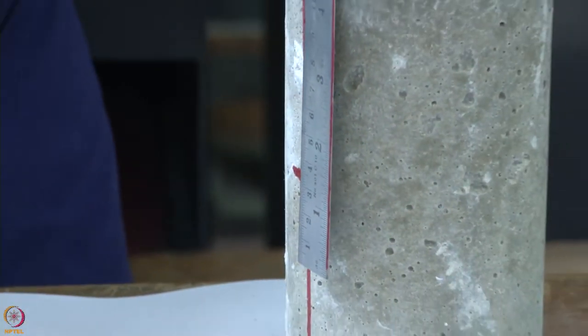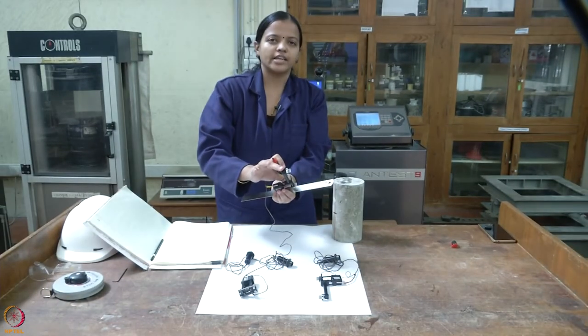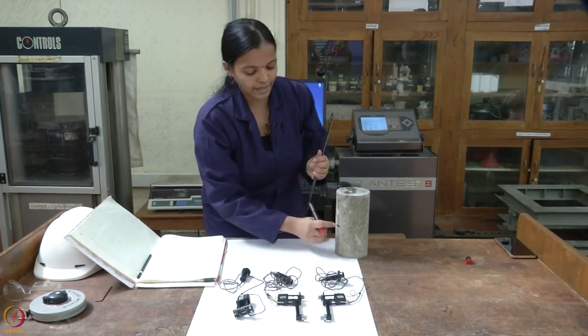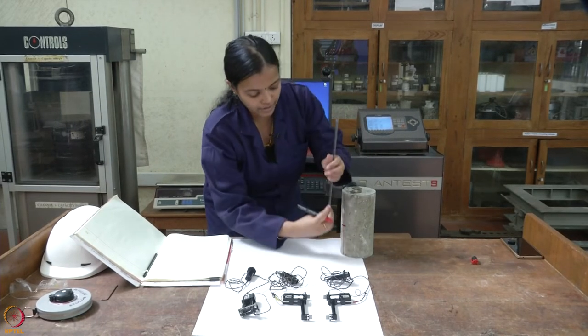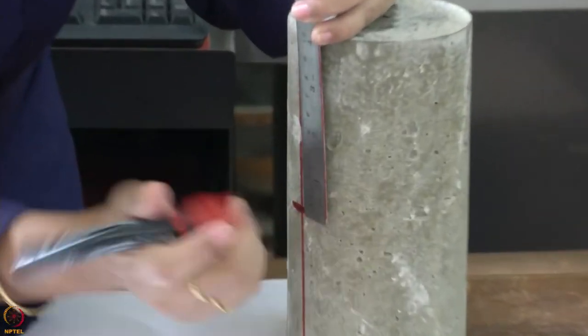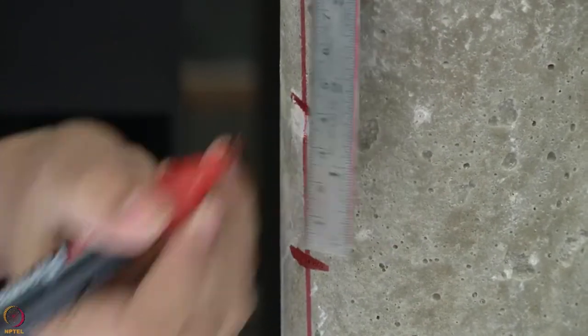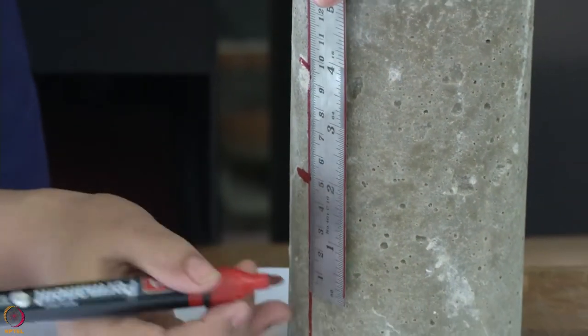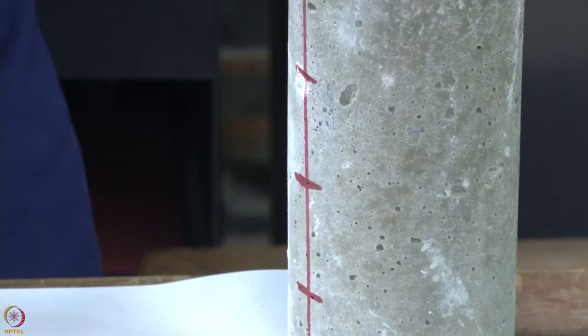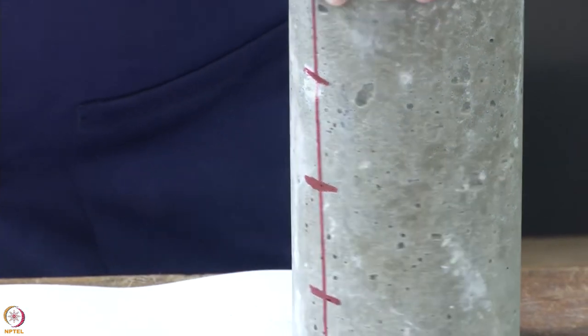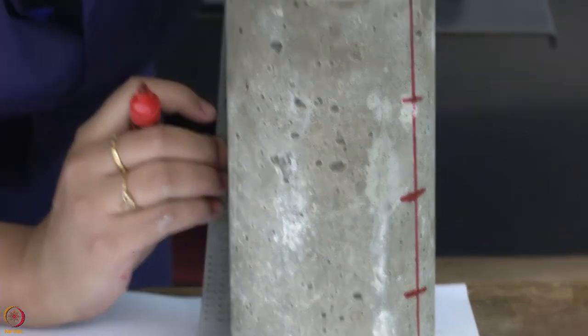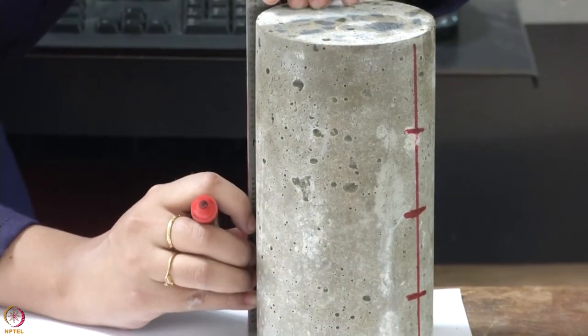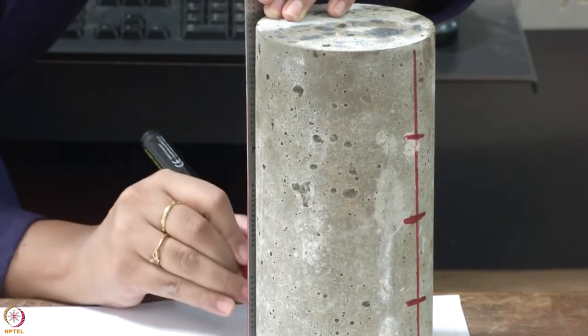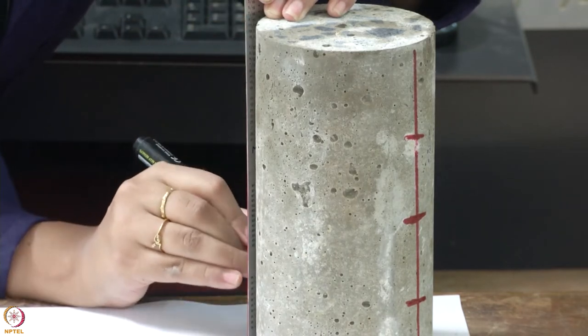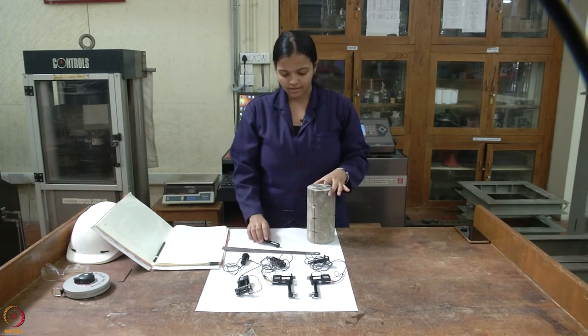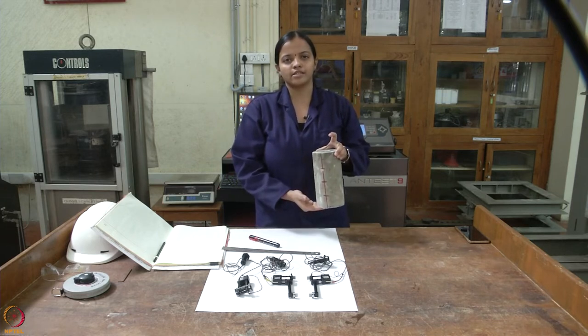Then in order to attach the extensometer, the extensometer gauge length is 100 mm. So I will be marking 50 mm above and 50 mm below the center point. In a similar way, we will mark on the opposite side. Now the specimen is marked. Now we take the specimen to the testing system and start the testing.